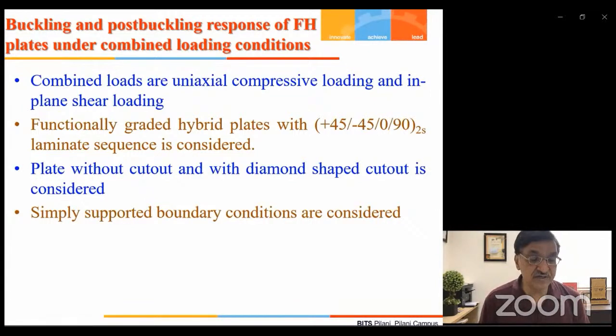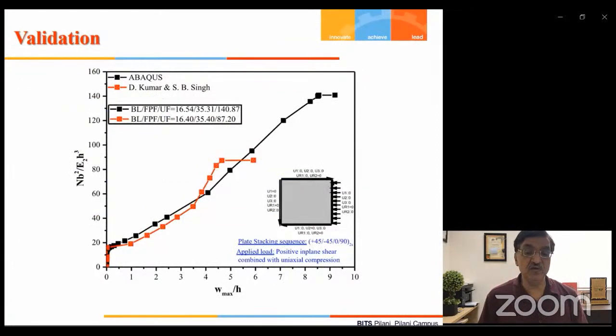Quasi-isotropic laminates have been considered, with simply supported boundary conditions, and plates without cutout and with diamond shape cutout. Verification of results was done against the literature. Only the ultimate loads are different from that study, because of a different philosophy and mechanism taken. In our case, ultimate load is based on loss of stability, whereas the available literature consists of a self-developed program based on failure criteria and self-developed material degradation models.